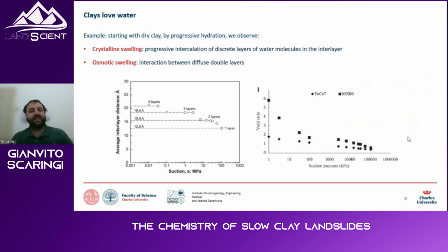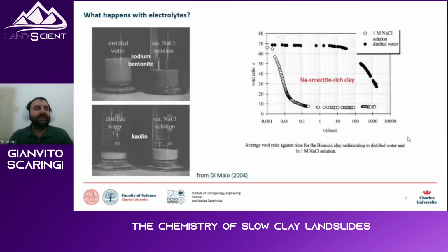water in the pores. This free water in the pores is what is responsible for the permeability of the clay, which is typically very low, and that's because most of the water, especially in certain types of clay, is actually adsorbed. It fills the surface of the clay. It's close enough to the surface of the clays to be electrically attracted. Only part of the water is free to move in the pores.